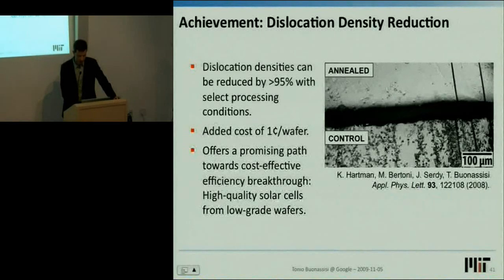So on the bottom part of this figure, we have a control wafer with these little pits that correspond to dislocations after the sample has been defect etched. And on the top, we have the annealed sample, which is essentially taken from an adjacent part of material where we demonstrate that the dislocations have been effectively removed. And we believe that this process, if done correctly, could be done for about a cent per wafer, a penny per wafer, which is really, really promising.